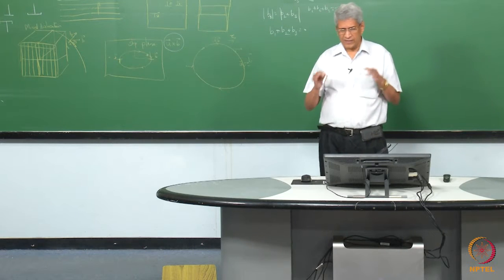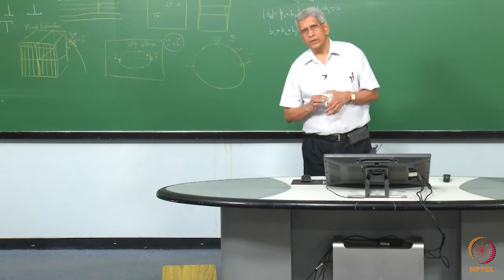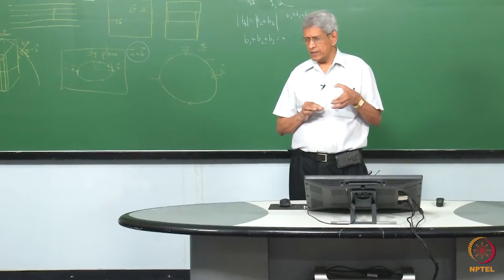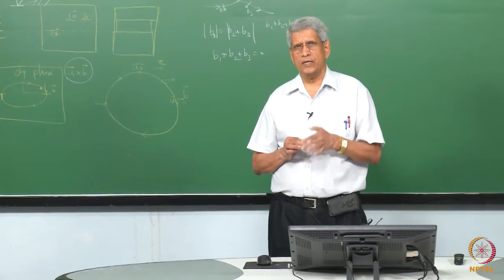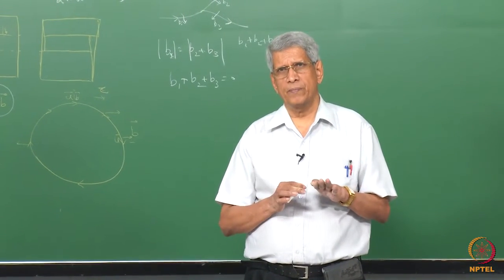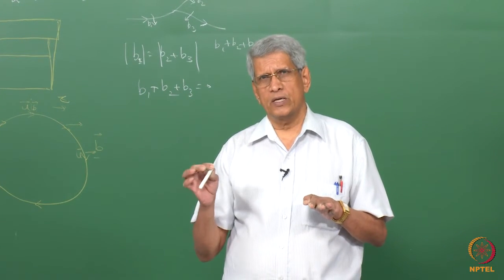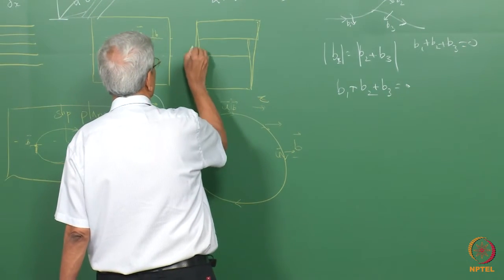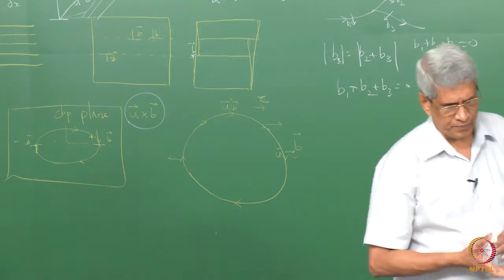This is exactly the same way in which a dislocation moves within that sample, or the dislocation imparts plasticity to the material. So, every time a dislocation moves and comes out of the sample surface, it has given a displacement of atoms by the Burgers vector, and when it comes out, a step of the order of a Burgers vector has been created on the sample surface.